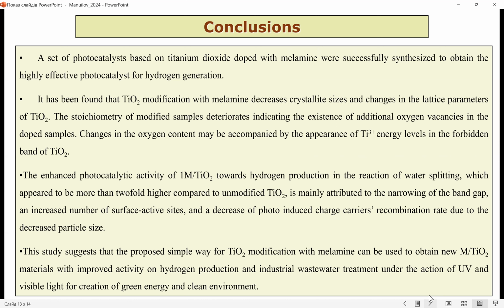The enhanced photocatalytic activity of 1M titanium dioxide towards hydrogen production in the reaction of water splitting, more than 2 times higher compared to unmodified titanium dioxide, is mainly attributed to the narrowing of the band gap and increased number of surface active sites, and a decrease of photo-induced charge carriers recombination rate due to the decreased particle size. This study suggests that the proposed simple way for titanium dioxide modification with melamine can be used to obtain new materials with improved activity of hydrogen production and industrial wastewater treatment under the action of UV and visible light for creation of green energy and a clean environment.